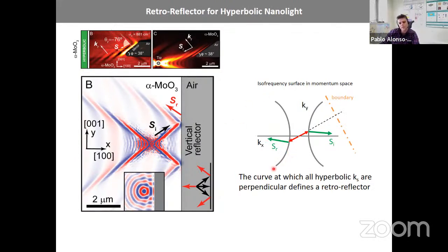So we thought, okay, what is the curve at which all these surface waves come back? Look here. This is the hyperbolic propagation, right? Here, K and S are collinear, is the only case, but here S goes in this direction and K is like this, perpendicular, and you have all different combinations in all these angles. So you need the shape of a boundary where, by momentum conservation of all these Ks that are rotating, they all make back reflection and they all come back to the origin. And this is, in the end, really an easy calculation. It's a hyperbola, it's the equation of a hyperbola.